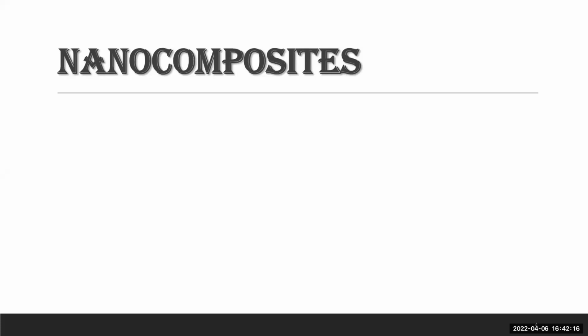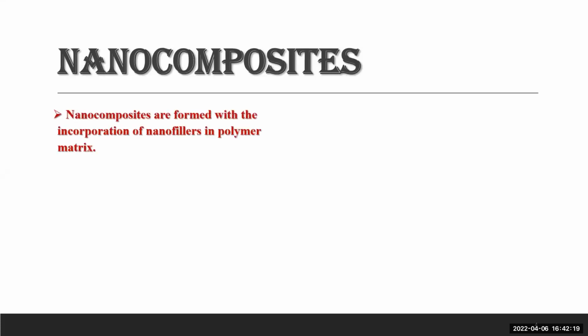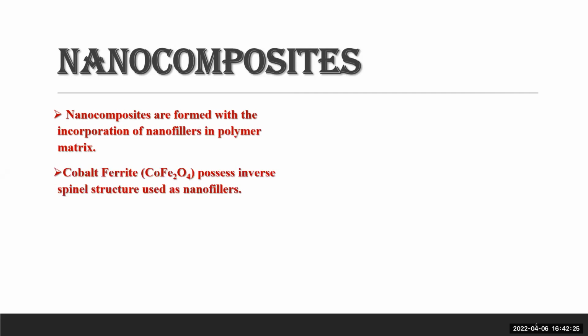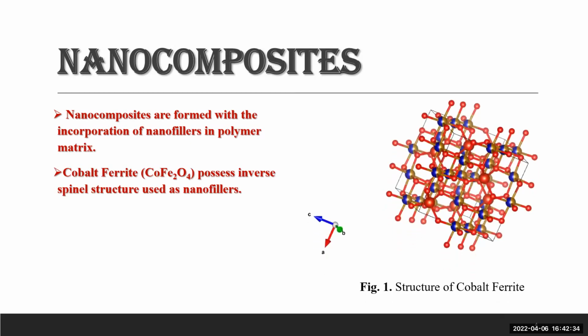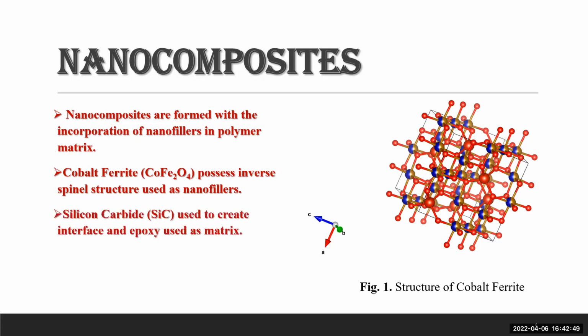Nanocomposites are the prominent material for these demanding applications. Nanocomposites are formed with the incorporation of nanofillers in the polymer matrix. For this purpose, we have used cobalt ferrite, silicon carbide, epoxy nanocomposite, where cobalt ferrite is a nanofiller having an inverse spinel structure. As you can see in figure 1, this is the inverse spinel structure of the cobalt ferrite nanoparticles, and due to the unique structure, it possesses excellent magnetic and dielectric properties. Then a hetero interface is introduced by adding silicon carbide with cobalt ferrite nanoparticles into the epoxy matrix to enhance the properties.